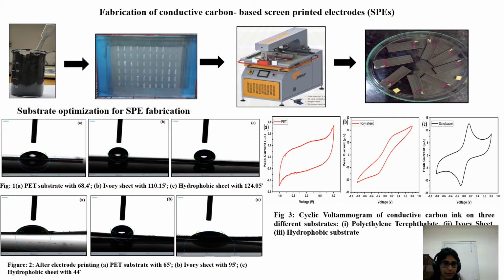For this, substrate optimization was also carried out, where three substrates were chosen. First is the PET substrate, second is the ivory substrate, and third is the hydrophobic sheet. Contact angle measurement was carried out on all of these sheets to recognize the hydrophobicity, and the hydrophobic sheet showed a theta value of 124 degrees in comparison to PET showing 68 degrees and ivory sheet showing 110 degrees. Also, after ink printing, the cyclic voltammogram of all three electrodes was taken, which clearly depicts that the hydrophobic substrate shows the well-defined oxidation reduction peak in comparison to the PET substrate and the ivory sheet.